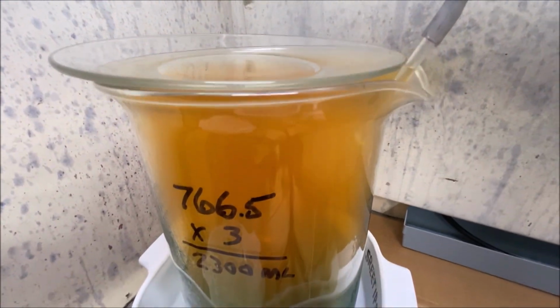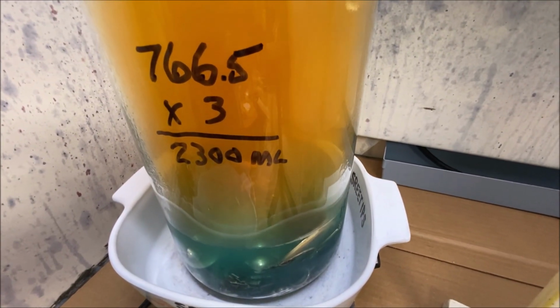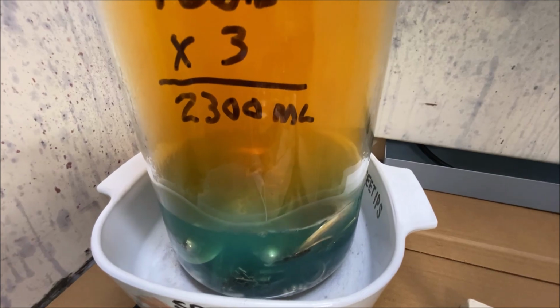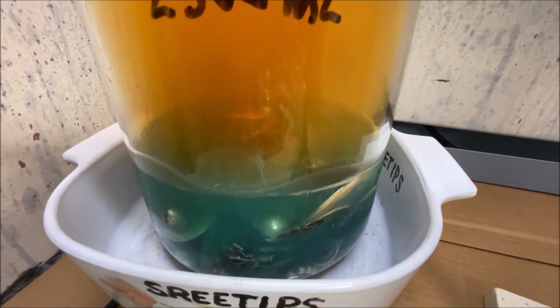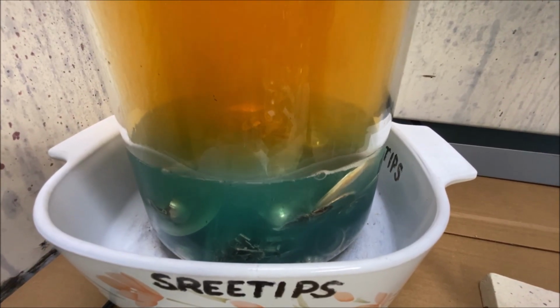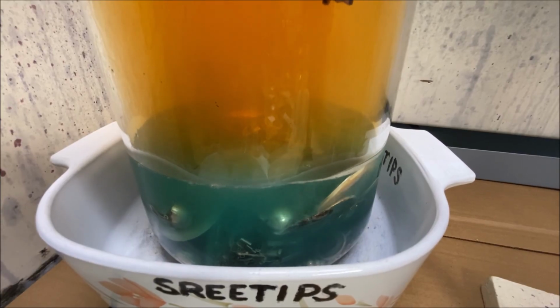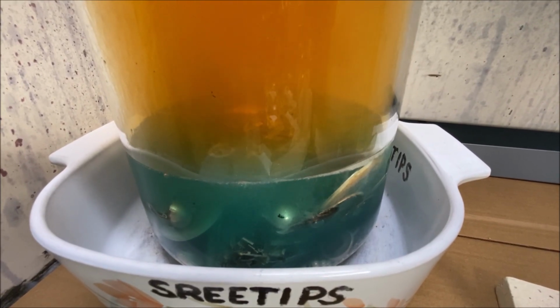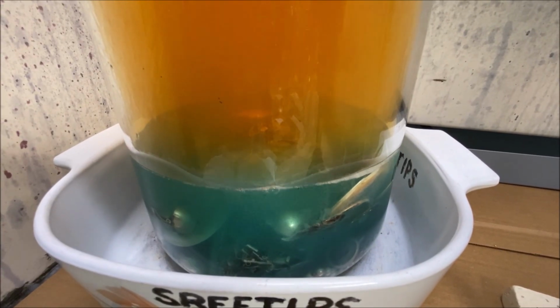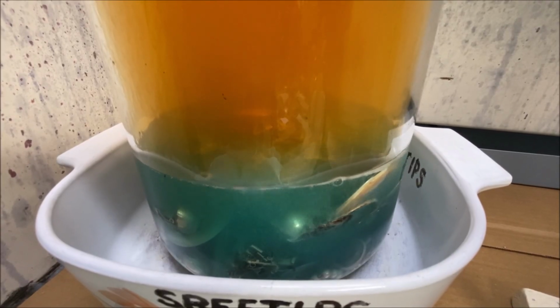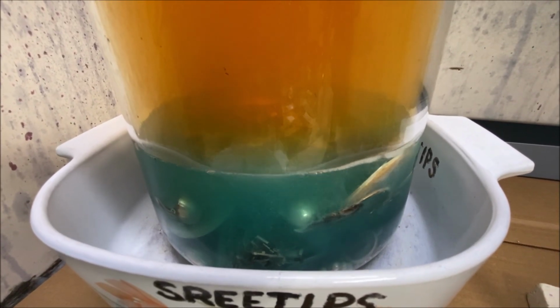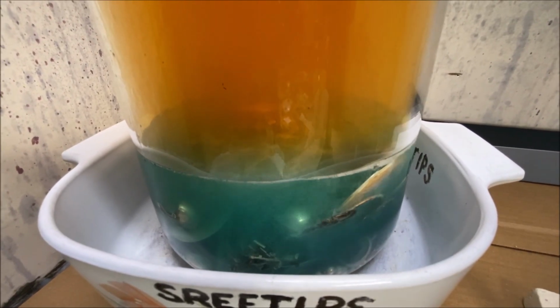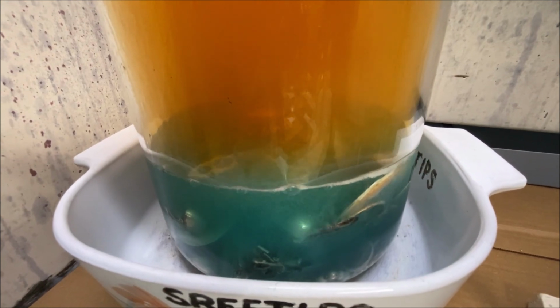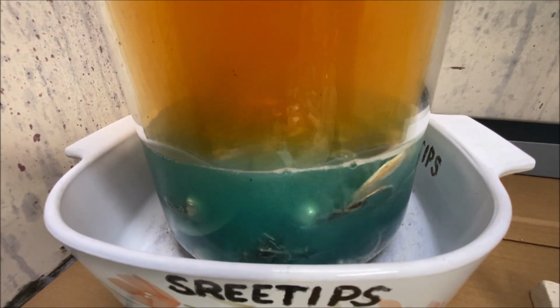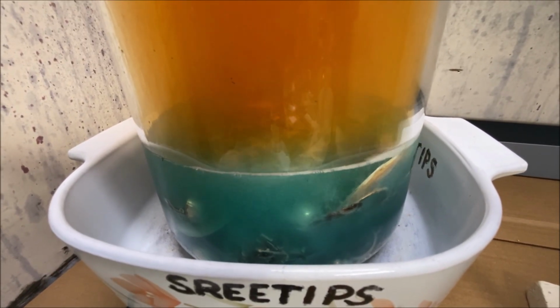What this will do is the nitric acid will find a way to get underneath the coating of karat gold in there. And once the nitric acid comes in contact with the base metal, which is going to be brass, the nitric acid will dissolve the brass out, but it will not dissolve the karat gold coating that's over the brass. It will leave that intact, and it'll form little shells of what these pieces used to be, and leave those intact, and then we'll recover those shells or foils and then refine the gold foils.